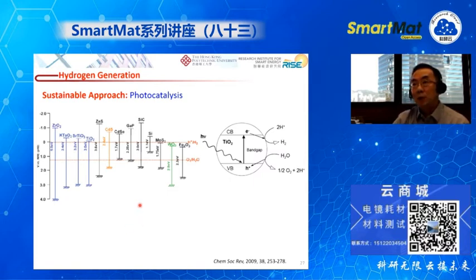And people can also use sustainable approaches to get hydrogen. For example, they use photocatalysis. When a photon shines on a photocatalyst, it excites one electron from the valence band to the conduction band. If the conduction band is more negative than the hydrogen evolution potential, it can generate hydrogen. And of course, if the hole left in the valence band has the right position, then it can also create oxygen by using this photocatalysis.